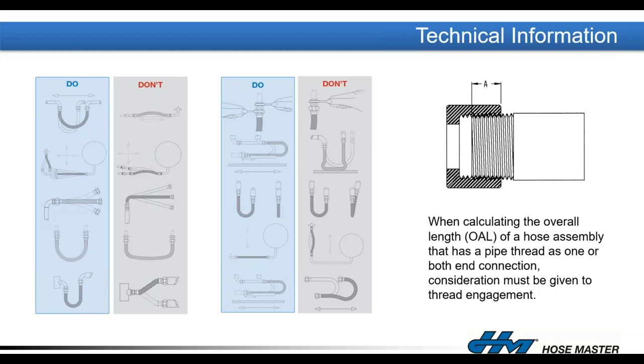The top, there's two columns here, the left-hand most column with the blue and the gray column. The picture on the top of the gray column, that hose is being compressed, as is the hose underneath it. And you can see how those hoses are compressed. They're trying to bend out of their own way, which can create localized overbending directly behind the fitting. And that's where most metal hoses fail due to overbending, is right behind that gray collar.